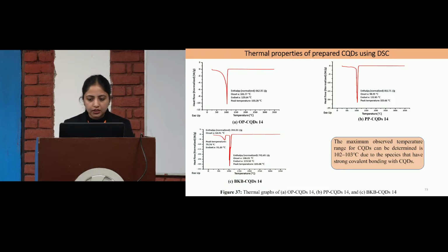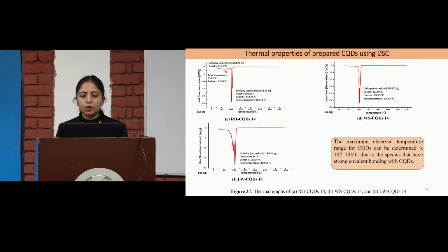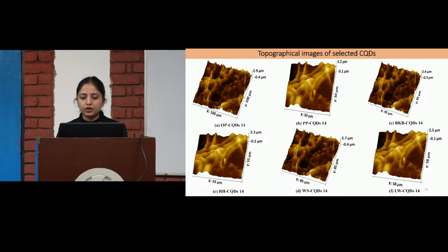So 102 or 103 is the maximum peak temperature at which they change their phase. So these are the thermal properties of the selected carbon quantum dots. Then the topographical image of the selected carbon dots is analyzed with the help of the AFM technique. AFM is atomic force microscopy. This tells us about the layers in the carbon quantum dot.